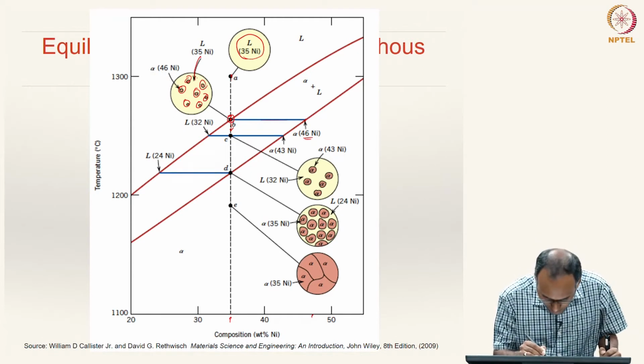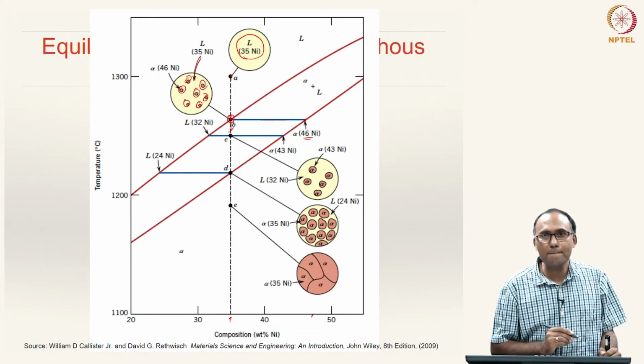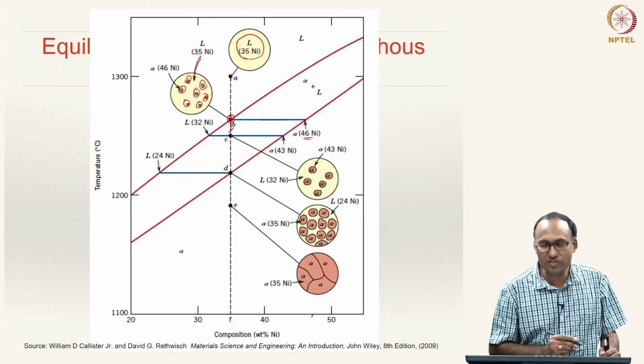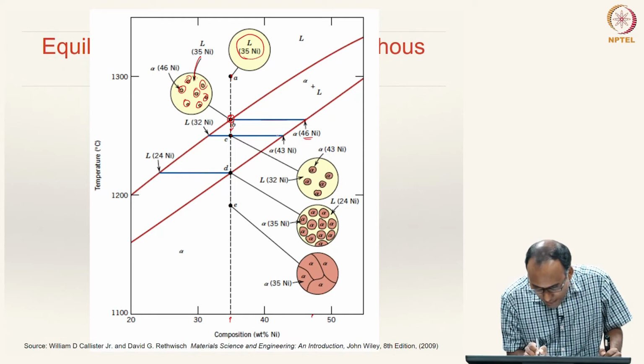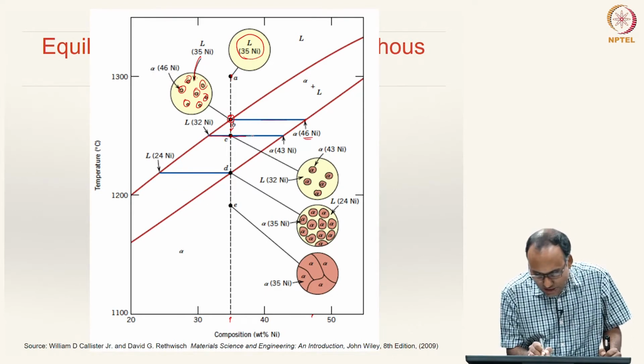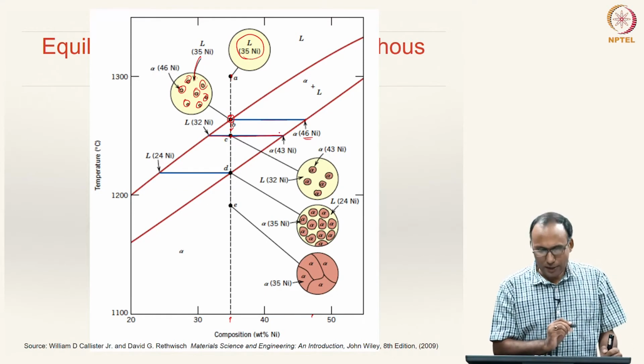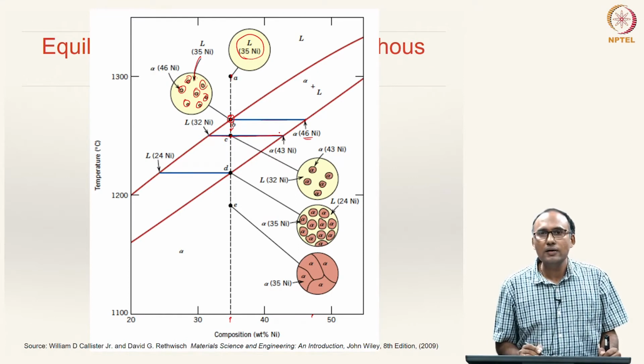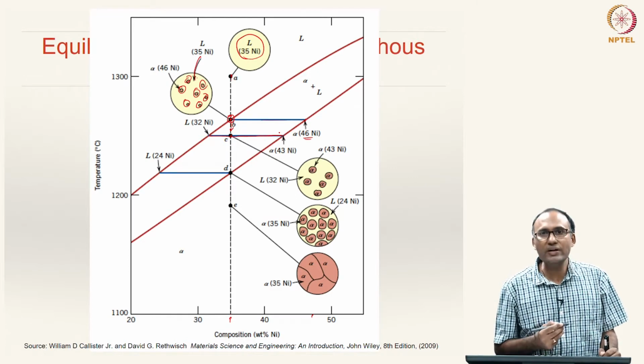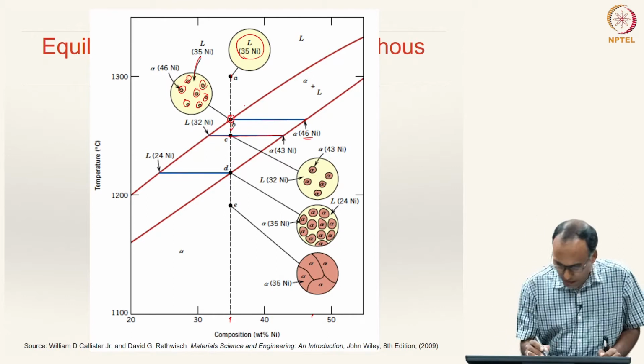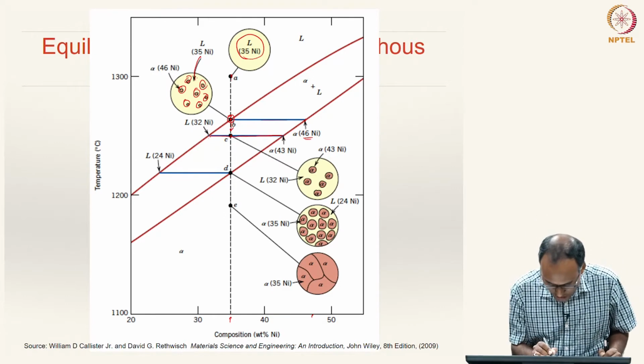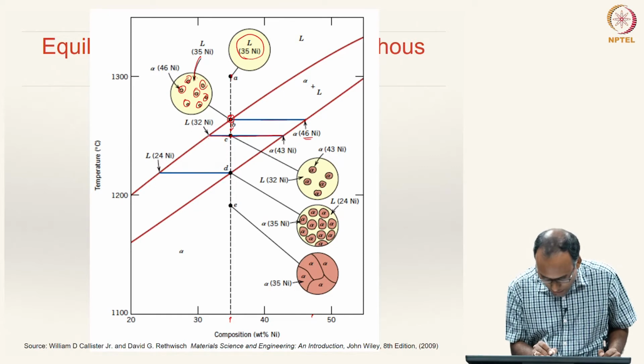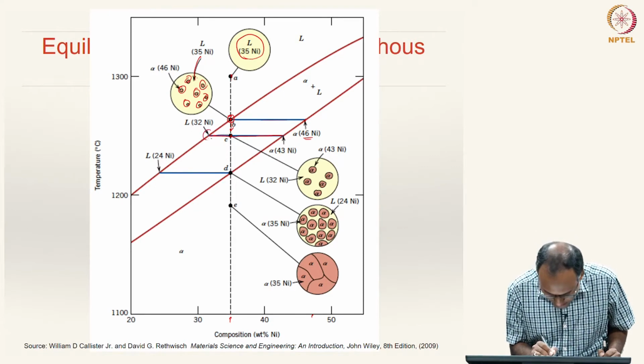When you are further cooling it down, let us look at point C. You are still in two phase region, and then you draw a tie line. This tie line is drawn, right. Now, let us look at the compositions of liquid and solid. So, this line hits the liquidus at this position. So, that corresponds to 32 nickel.